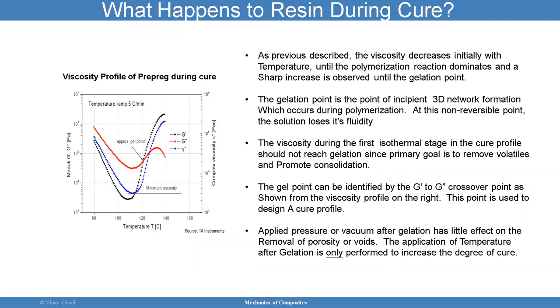Does that make sense? The gel point can be identified by G prime and G double prime, the storage modulus and the loss modulus. Whenever they cross, you can call that the gel point, and that's shown here in this picture. This point is used to design a cure profile. You know when the gel point is, so you can use that information to then design your cure cycle. Now, usually you don't have to deal with that. Usually the supplier has done a lot of testing, a lot of thinking about what works and what doesn't work.